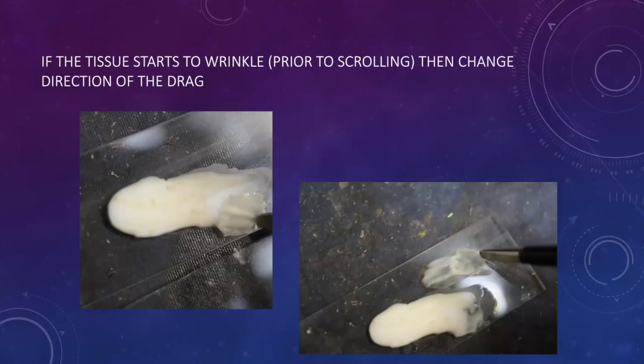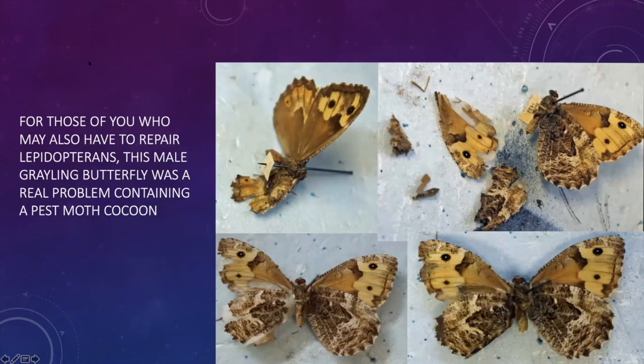The butterfly is stable and can be put back in the collection again. So if this tissue drags, and when you're dragging it starts to wrinkle, then change the direction of the drag. As you can see here, it's starting to buckle slightly. You get this sort of cockling effect as well. So I move the tissue upwards, flattening it out again as I did so. So it's a very useful technique to be able to know.